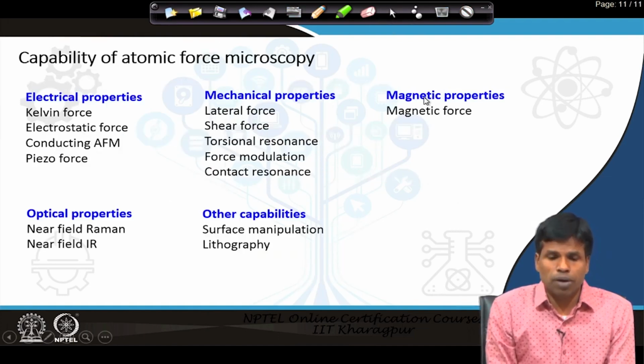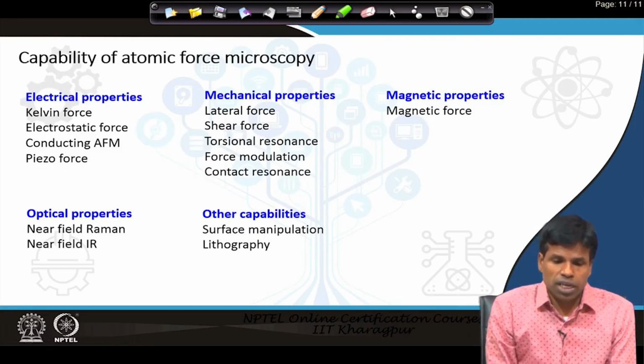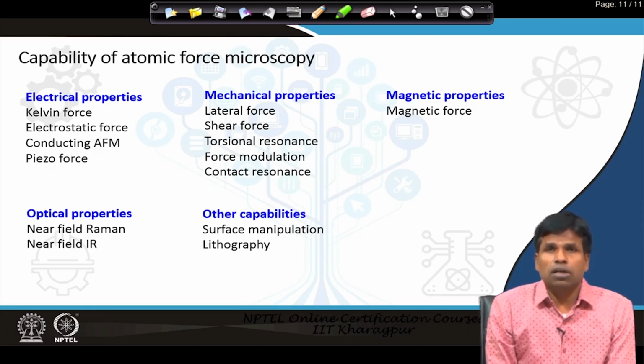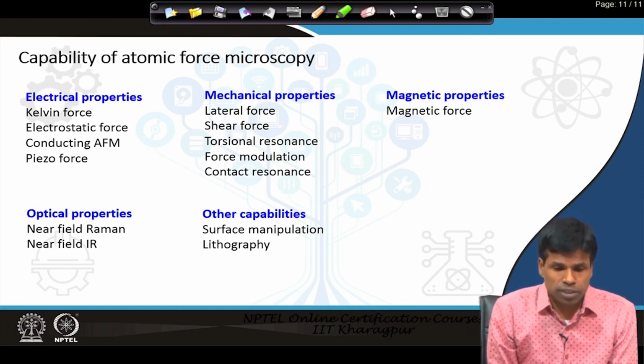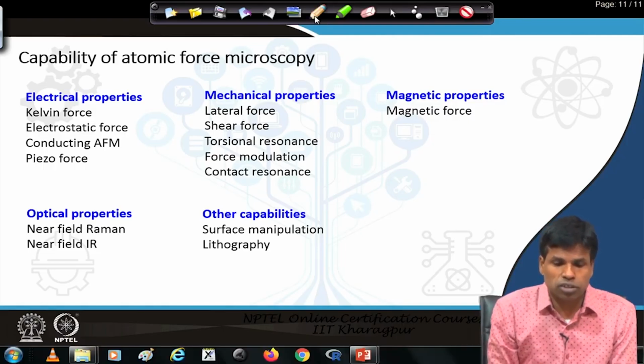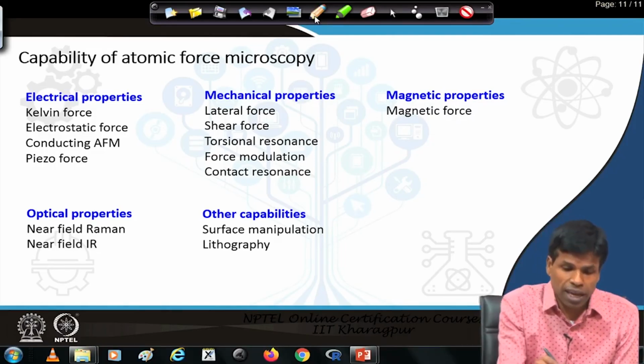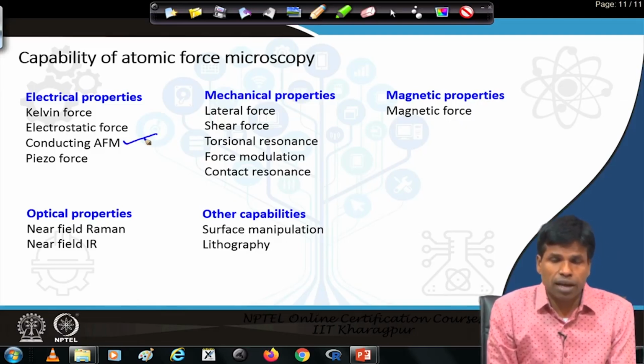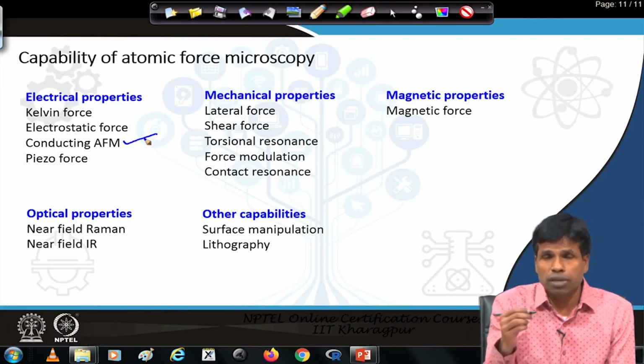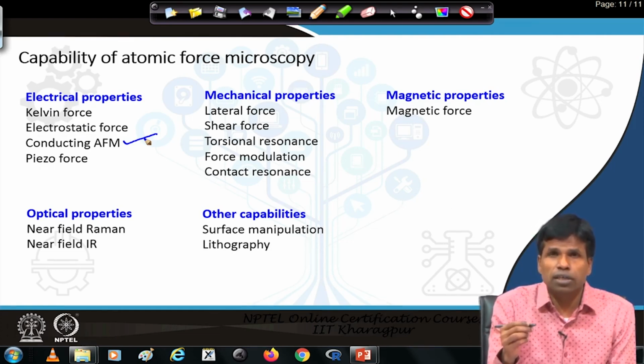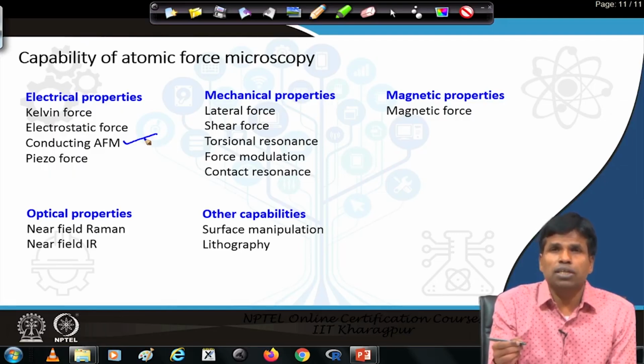So, if we look at the capabilities of the atomic force microscope, it provides us different material properties, including the electrical properties. Electrical properties are normally measured by Kelvin force microscope, electrostatic force microscope, conducting AFM. Here we say conducting AFM. In case of conducting AFM, the tip has to be conducting in nature, though theoretically we do not need a conducting tip, as we have seen in the first invention they have used a diamond tip.